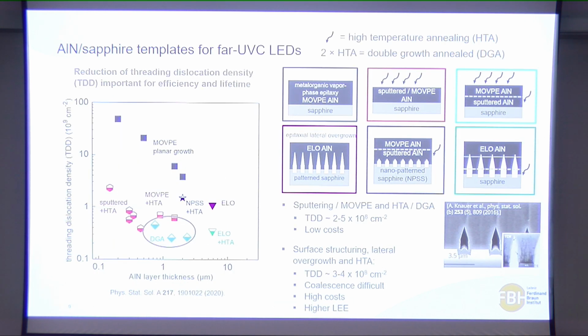And I'm not going to go into detail on the slide. I just want to give you an idea of the different approaches that we have used to actually get low threading dislocation densities. So basically the first way is a very simple MOVPE growth of aluminum nitride on sapphire. It's good because you can reduce the threading dislocation densities, but you need to go to very thick layers in order to get a lower threading dislocation density, and then that leads to cracking of the layers, and that's not good for your device.